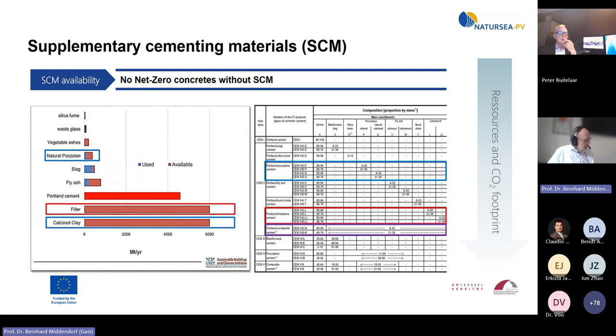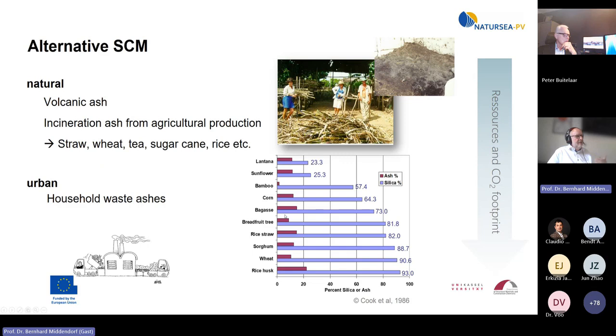In the talk from Bernd Arup he said that he used once a CEM II Portland limestone cement instead of a pure CEM I. So I think in the future we have to work on using different kinds of more eco-friendly cements. And then we also have our alternative SCMs, that means volcanic ash, I told you, and also agricultural ashes from straw, wheat, sugar, and what you see here. The point is the ash content of the plant. Look here, rice husk: when you burn it, you have 20% ash, and in the ash you have 93% silicate, which will react. Then we have to identify what kind of material we can use as SCM in cements, which we can use for UHPC.